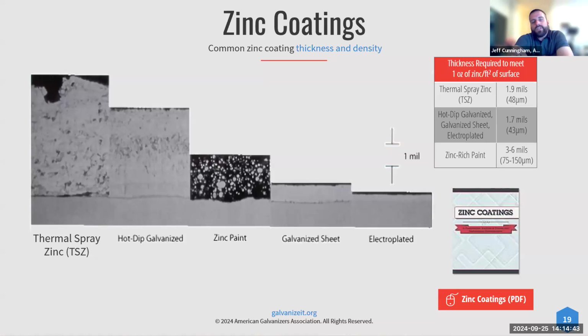So there are other zinc coatings out there. I mentioned this at the beginning. Sometimes they get lumped in with hot dip galvanized steel or confused, so we like to lay them out so you know the differences. Here are all the zinc coatings in cross section. Starting from left to right is zinc thermal spray, hot dip galvanized steel, zinc rich paint, galvanized sheet, and electroplated. You can see right off the bat that metallurgical bond, how dense and tight that is. Thermal spray is close, about 85% as dense, but this is a good way to start to show that it's a thick coating, and it's dense, with that metallurgical bond.